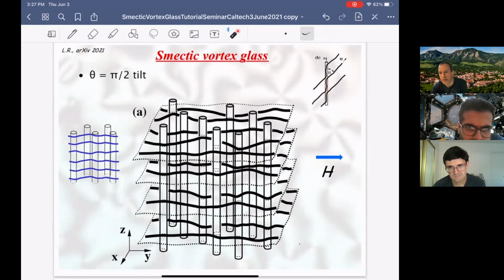So what I believe happens is, as a function of angle, you actually increase the effective point disorder that the flux lines, the vortices, see, because they're attached to this column over this finite length scale. So in fact, this allows you to tune the strength of the effective point disorder of the cross sections, which are now little stubby columns of finite length. And so there's a whole story there that, like I said, I have not fully developed. But let me just leave it with these comments. Thank you.